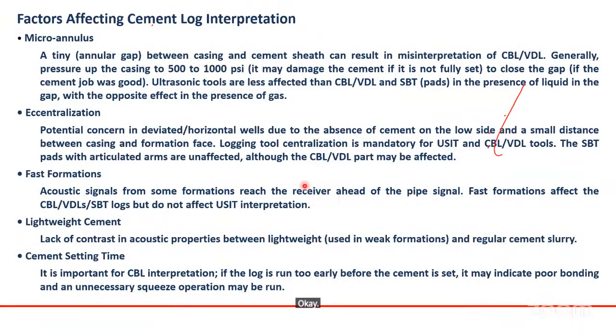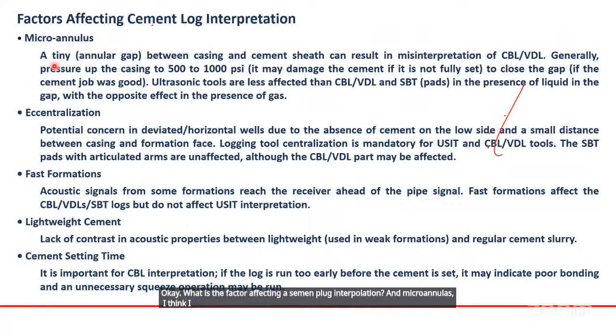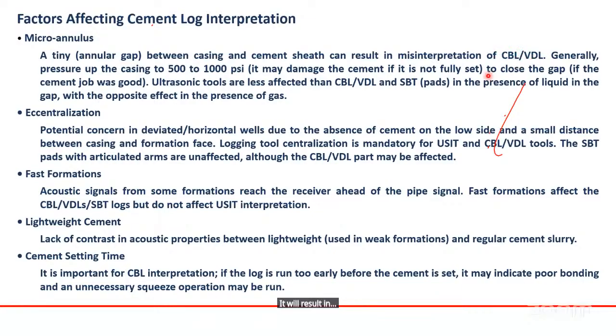Okay. What are the factors affecting cement log interpretation? Microannulus, I think I explained it. It's a tiny annular gap between casing and cement, which will result in misinterpretation. Generally, pressure up casing 500 to 1000 psi. This is important. If the cement is not set completely and you pressurize it and inflate it, this will create more gaps. So we have to be careful about pressurizing casing before cement is set. It will create another gap. Okay, it may damage the cement if it's not fully set, to close the gap, if the cement job was good.